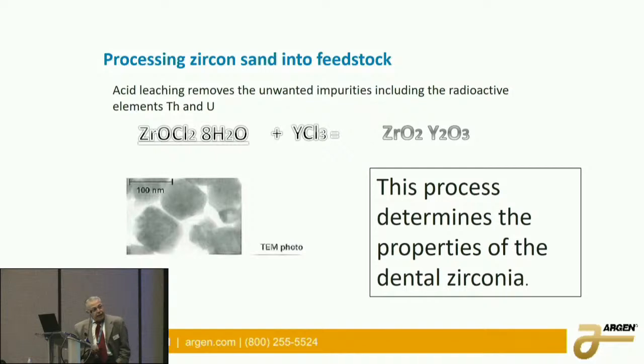Anyway, what you do with this feedstock determines how well the material is going to perform. And this process determines the majority of the properties of the zirconia. In our case, we add the yttria as a chloride right into this feedstock. And that gives us a very intimate pairing between the zirconia and the yttria oxide.